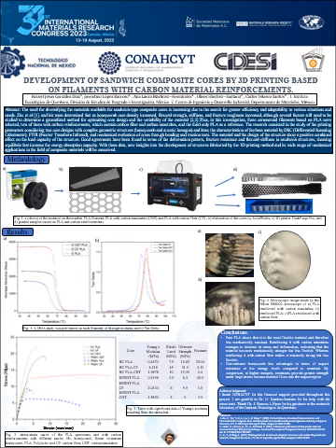So, conclusion. First one, the pure PLA shows that it's the most flexible material and therefore less mechanically resistant. Reinforcing with carbon nanotubes managed to increase its stress and deformation, indicating that the material becomes mechanically stronger but less flexible. Whereas reinforcing it with carbon fiber makes it extremely strong but less flexible.